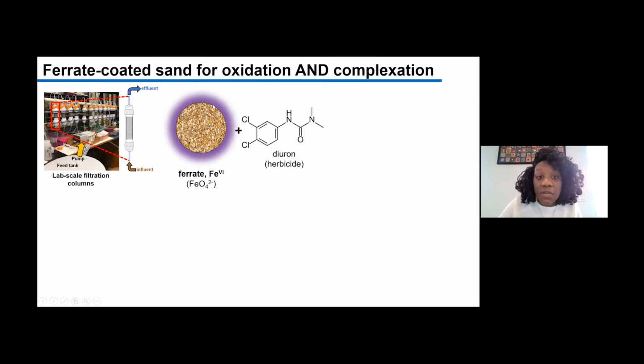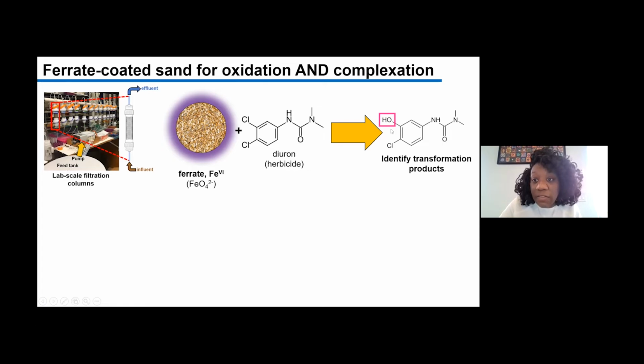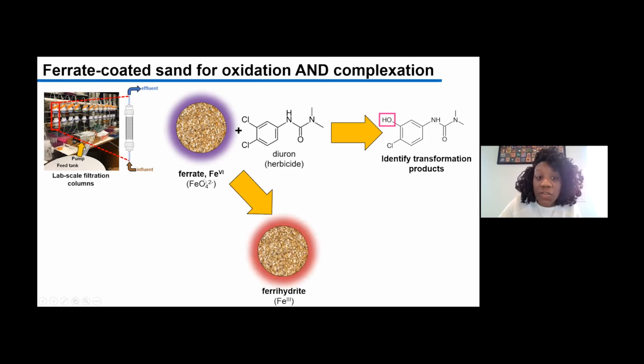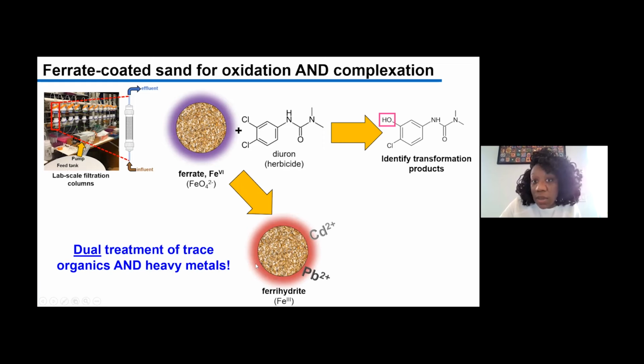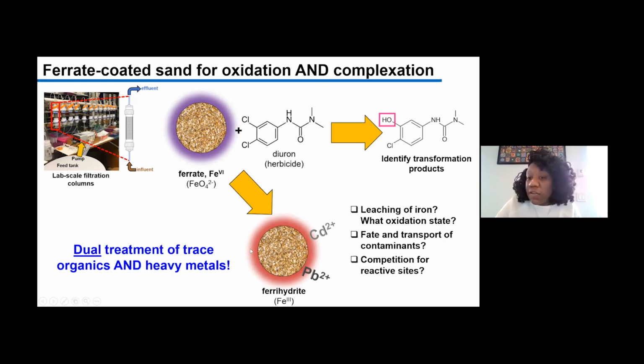So the idea is if you react this material with some representative stormwater runoff organic compound like diuron, this herbicide, it will help facilitate oxidation of the contaminant into a form that's more biodegradable than the parent compound. Once this reaction occurs, the ferrate will be reduced to iron 3 species. And then the iron 3 species is very well documented to help adsorb trace heavy metals as well. So we get essentially dual treatment of trace organics and heavy metals by one engineered reactive material that's also environmentally benign. So we are investigating the leaching of the iron oxide, the reactivity, what oxidation states are present on the coating and in solution, what's happening to these contaminants as they're interacting with the media, and what happens when you have competition of contaminants for reactive sites.